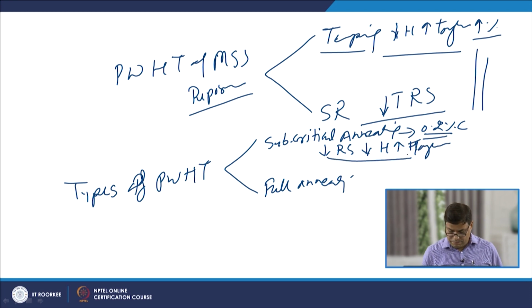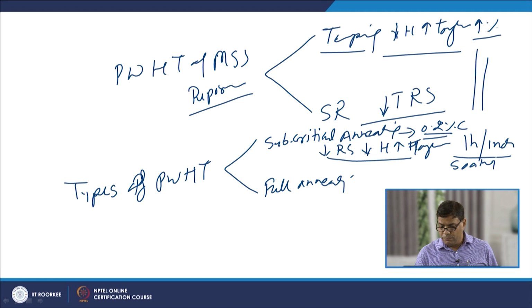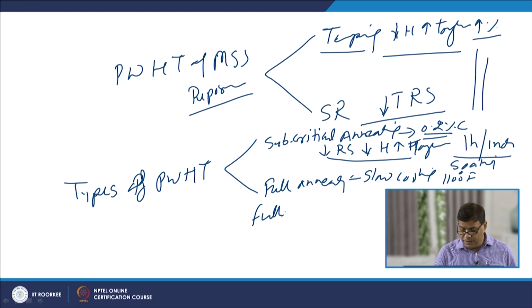So, these are the three main responses which are realized when subcritical annealing is performed, and 1 hour per inch of section thickness is the kind of soaking time which is given for subcritical annealing. On the other hand, when full annealing is carried out, exposure is given at a higher temperature, and thereafter we apply slow cooling, especially up to 1100 degrees Fahrenheit, and thereafter air cooling can be given, and this gives us the fully ferritic structure, which helps in lowering the hardness.